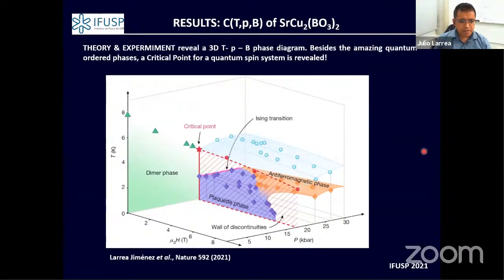So to summarize, our experimental result in this Strontium-copper borate, we have the combined effect of temperature, pressure and magnetic field, and we managed to define a three-dimensional phase diagram. A quantum phase transition sets in this system, with the coexistence of a plaquette phase and dimer phase, and this quantum phase transition terminates at a critical point at finite temperature.